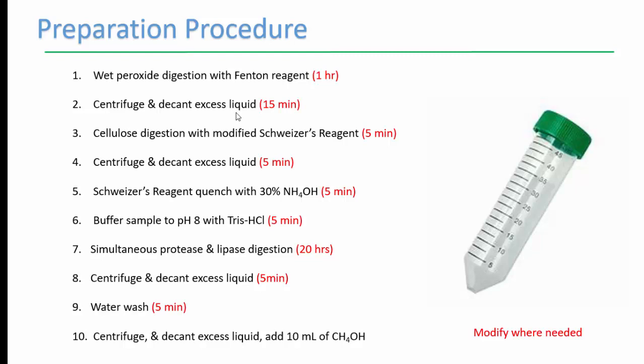We always suspend the plastic particles finally in methanol, and that is to keep it from adhering to the walls of the container, keeps them in solution. And then when you plate the particles out onto a microscope slide, the methanol will evaporate, and so now you have a clean matrix that you can put in the instrument.